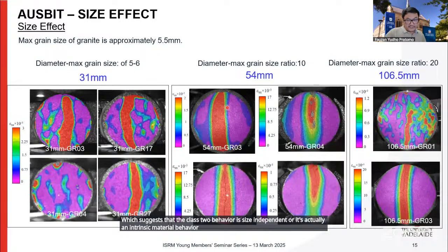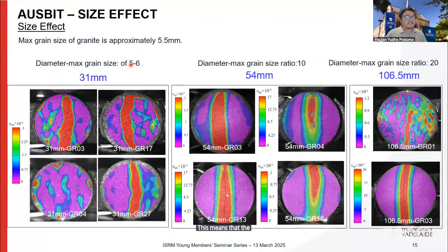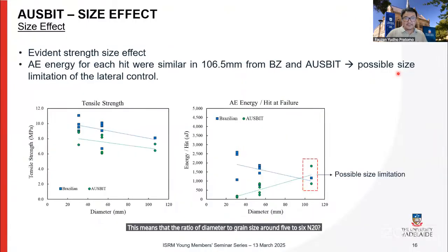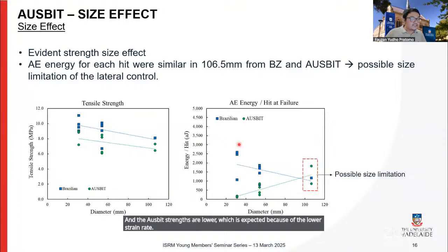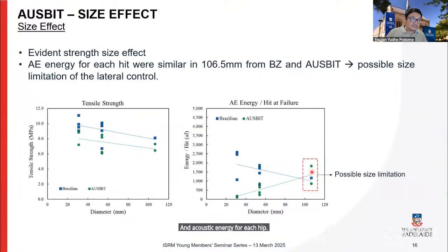Here the further DIC contours are shown, and since the maximum grain size of the granite is around 5.5 millimeters, the size of the largest quartz, this brings the ratio of diameter to grain size to around 5 to 6, 10, and 20. And there is evidence of a straightforward strength size effect. The AUSBIT strengths are lower, which is expected because of the lower strain rate. And the acoustic energy for each hit was somewhat similar in the large sizes for both Brazilian and OSBIT, which suggests there is a possible size limitation of lateral control.